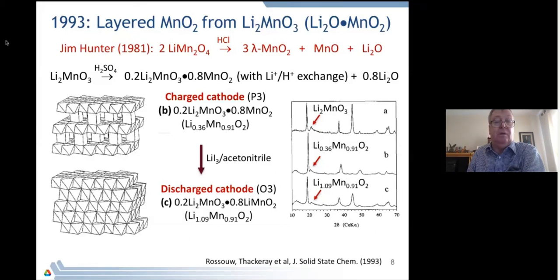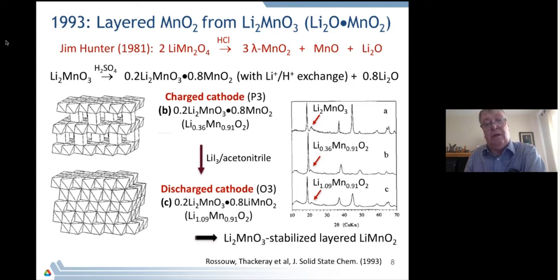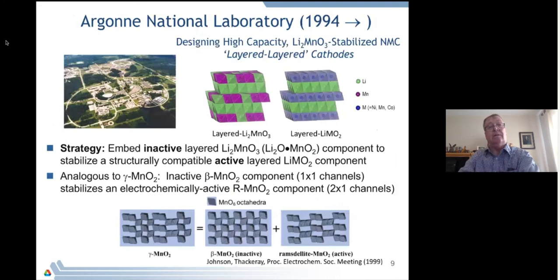Once one reinserted the lithium under non-aqueous conditions, either chemically or electrochemically, we created a discharged cathode, which consisted of two components, Li2MnO3 and a layered LiMnO2 structure. So this gave us some thoughts of using Li2MnO3 to stabilize layered materials. In 1994, I left the CSIR in South Africa and headed towards Argonne National Laboratory in the United States. And we used the work that had been done at the CSIR largely as a platform to continue studies on lithium manganese oxides. And we used this idea of Li2MnO3 to stabilize layered NMC type materials.